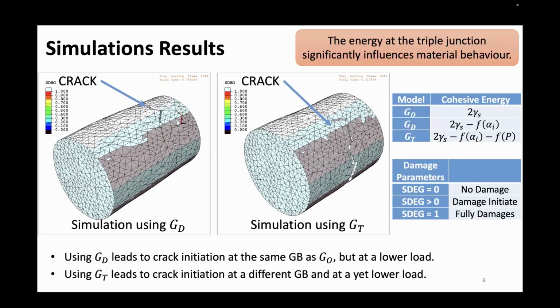That's the cohesive energy calculation for the different models. When we use GD with disorientation, it leads to crack initiation at the same grain boundary as the GO model, which also considers the disorientation, but at a lower load. When we turn our attention to the GT model, where we consider the triple line disclination power, you notice that the crack initiated earlier, at a lower load, and at a different grain boundary. It also propagated much quicker. So the key takeaway from this slide is that the energy at the triple junction significantly influences the material behavior, specifically where the damage initiates and how it propagates.